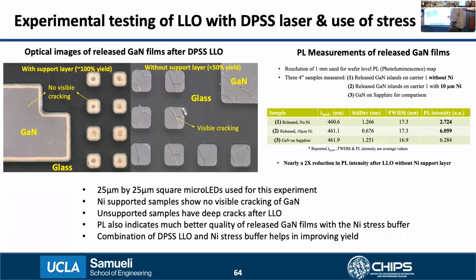But under the same process conditions, when we don't use any nickel layer, nearly 50% of the devices have cracked significantly. This was also confirmed using PL measurements, which showed that when we don't use nickel, the PL intensity falls by around 2X compared to virgin devices on sapphire. But when the 10 micron nickel is used, the PL intensity is essentially comparable. So this also confirms the results of the modeling that we had done earlier.